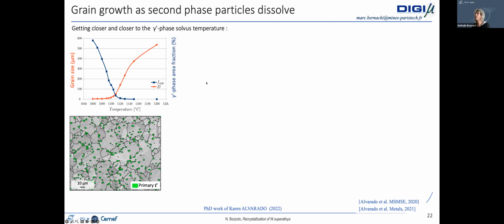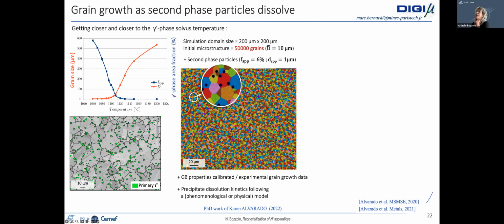So this has been modeled using the DIGIMU software. In a simulation domain, which included initially 50,000 grains with a size of 10 microns, and with small second phase particles, which you can see better here in the zoom. The second phase particles account for 6 percent area fraction, and have a size of 1 micron.